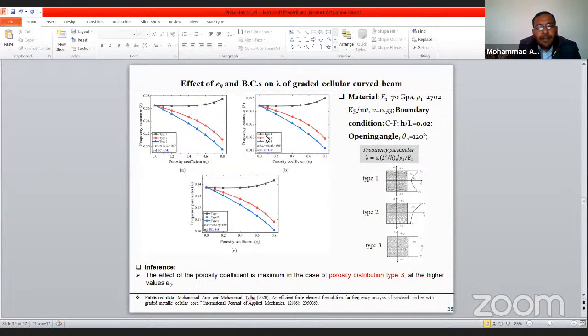Here, the effect of porosity coefficient, as I discussed earlier, and the boundary condition on the frequency parameter of the functionally graded curved beam. Here also, I have considered three different types of porosity distribution for the graded cellular structure: type 1, type 2, and type 3. The geometric and material properties are given here, the opening angle is just 120 degrees, and non-dimensionalized parameters are also taken here.